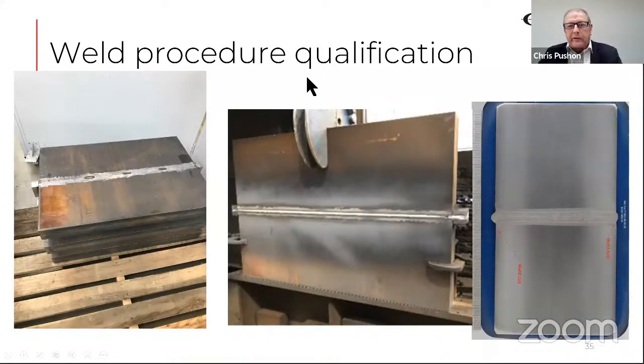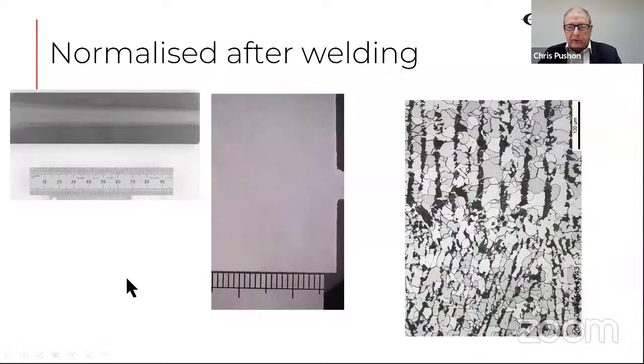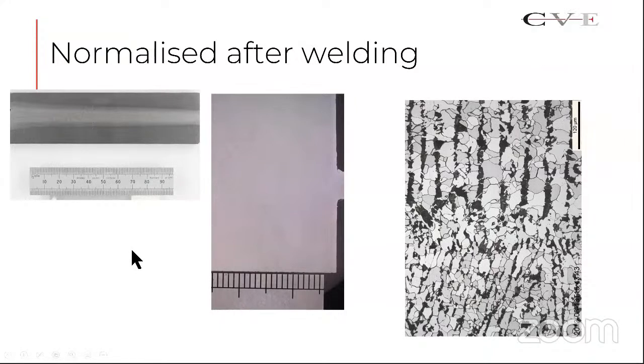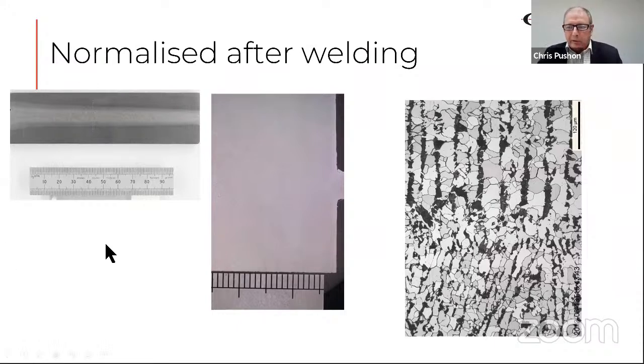So what we've since done is gone through a process for qualifying the weld procedure and to gain approval from the regulator. So these are test panels that we've welded, and these have been subjected to some quite serious mechanical testing campaign. And at the time of talking now, we have an approval for linear seam welding from the regulator.